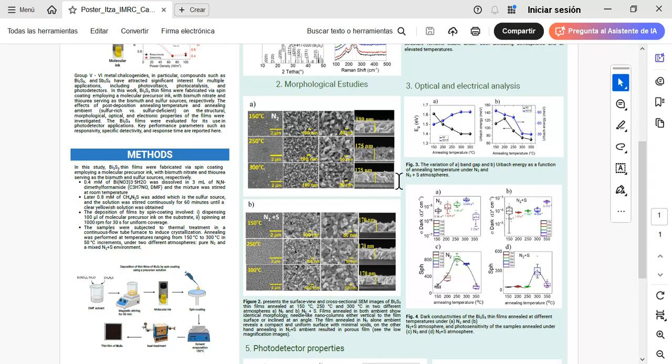This is according to the literature. The band gap value is influenced by factors such as stoichiometry, crystallinity, and morphology. For both sets of samples, the crystallinity and morphology were very similar. Therefore, the observed variation in band gap can be attributed to different stoichiometry.